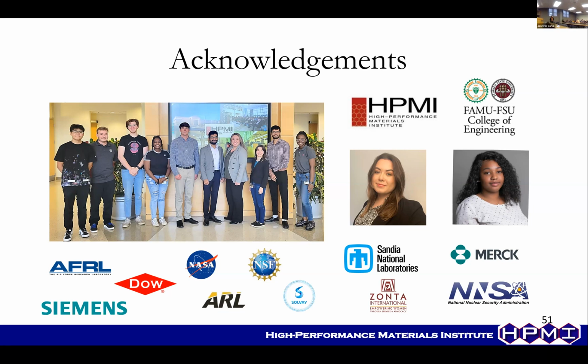Thank you very much. So are there any questions? Yeah, go ahead. In terms of the thermoset with BNNTs, have you done thermogravimetric analysis by any chance to observe the decomposition weight loss under a controlled environment? Yes, we have done. That was actually to determine what the weight percentage of the BNNTs was. The decomposition was, I think, around 350 degrees C, but under a more controlled but extended period. So that TGA would take it up to about 1,000 degrees C, and we held it until we had that decomposition. But yeah, it does decompose under lower settings when you put the entire sample in there in a small amount. Does that answer your question?